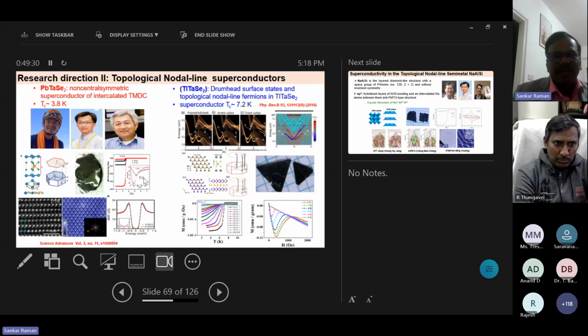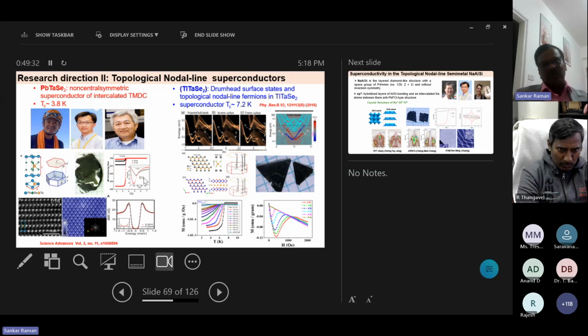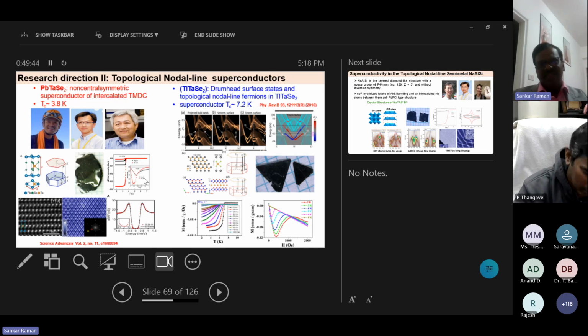The same family I tried with the thallium one. You people know how poisonous thallium is. But thallium gives a centrosymmetric topological nodal material. We grew this one and prepared almost 7.2 K superconductivity. We almost doubled the superconductivity. And we published in Science Advances, including Nature Physics, on this material.